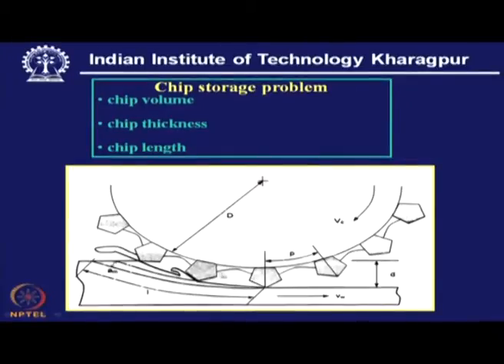Here we have the grits arranged over a periphery, and this is the space available ahead of each grit or cutting tool, and this space must be adequate so that this volume of chip, which is shown here, can be well accommodated, and once this chip pocket leaves the workpiece surface, the chip will be thrown out by centrifugal action. So, from this starting point to this termination, the material should be held with adequate chip storage. Now, the chip storage demand will become quite high when the material removal rate also becomes quite high. So, these are the restrictions imposed by the conventional bond.